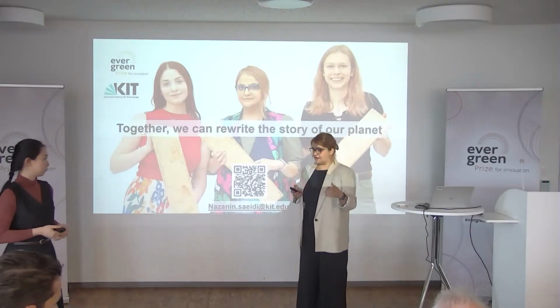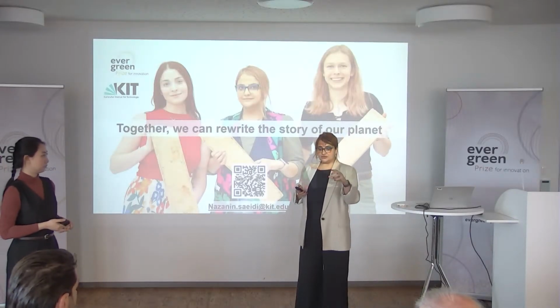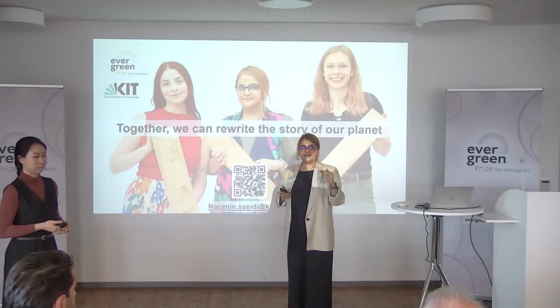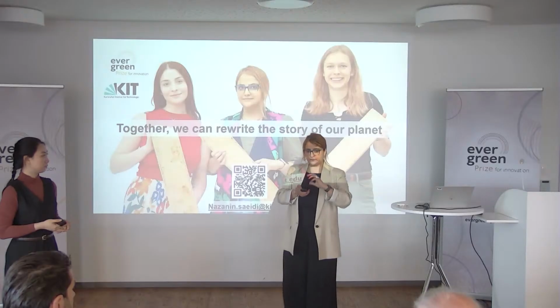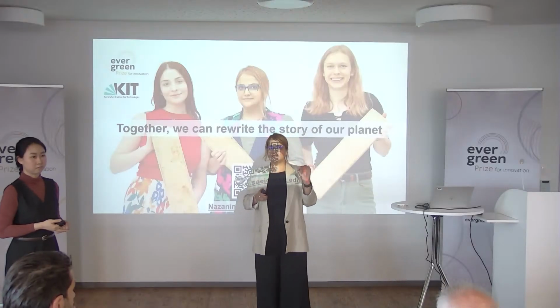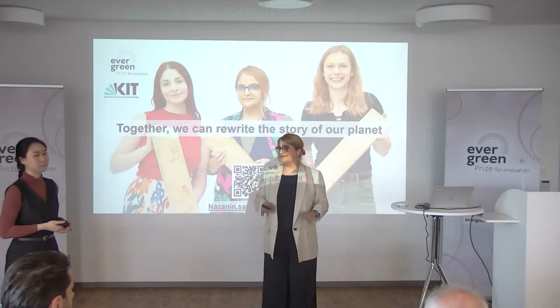Yes, when we densify it, the weight to strength ratio improves, but we cannot densify too much because over-pressurizing the mycelium materials would cause delamination. So we found the sweet spot more or less is about 800.